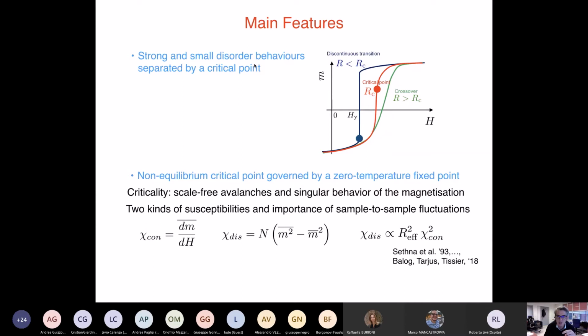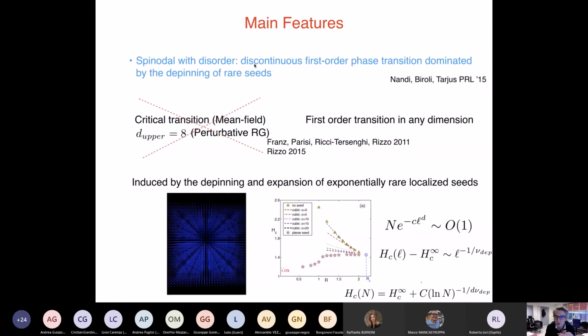This other feature was found more recently, and we found it with Sarojini Nandi and Gilles Tarjus. Now, if you are in the phase in which you have a discontinuous change of the magnetization, this is in a certain sense the most interesting phase for the problem of the yielding transition. It is a phase in which you perturb an extended state at a certain point, you have a failure of the state, and it goes to the other one. So it's a little bit similar to what we could think of as the yielding transition.